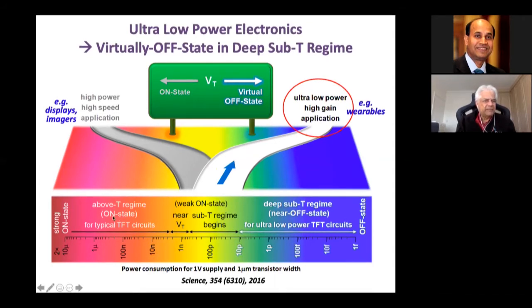Here, at gate voltage values much larger than the threshold voltage, you get the high power, high speed application areas, like displays. If you went out and bought an OLED TV, one of these LG or Samsung TVs, they're all operating in this regime as far as the driver of the organic light emitting diode is concerned. This is a fairly new regime that we have discovered in thin film transistors. Subthreshold regime operation has been reported for silicon, and I'll show you some data later. But the attractiveness of using a wide bandgap material is that the currents can be very low. If you take an oxide transistor, the off-state current is extremely small, way smaller than any sensory current that comes out of a low output response sensor.